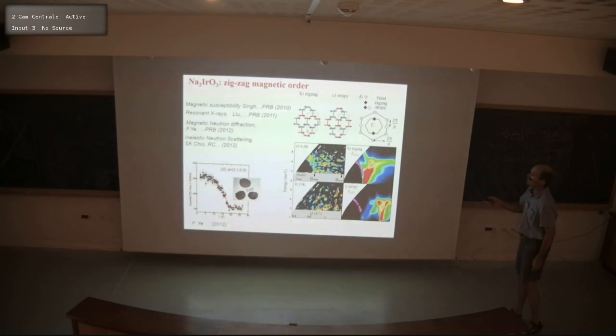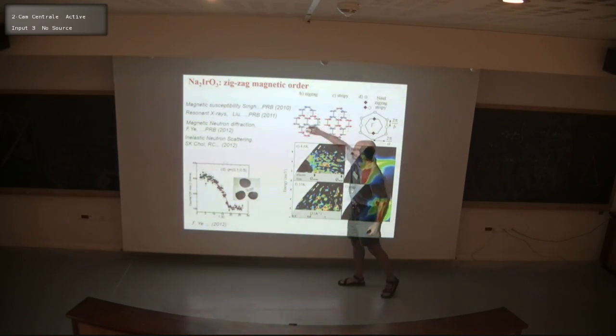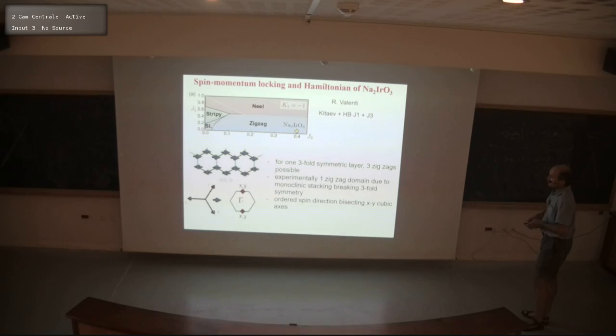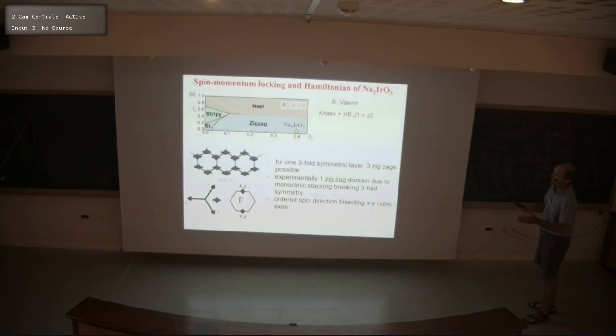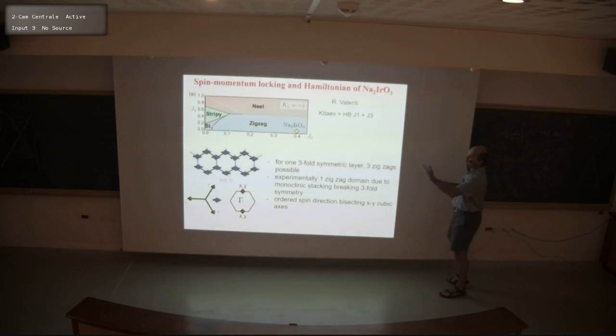So briefly, I'd like to mention also some key experiments done on sodium iridate, which give evidence for Kitaev interactions in this material. So through a combination of thermodynamic and also resonant X-rays, magnetic neutron diffraction, and also inelastic neutron scattering, it's been possible to uniquely converge on the magnetic order, which has this zigzag form in this material. So spins form ferromagnetic zigzag chains that alternate in orientation as we go vertically along the honeycomb structure. And various DFT calculations suggest that, in fact, this can be stabilized, but only if one includes a number of terms in the Hamiltonian.